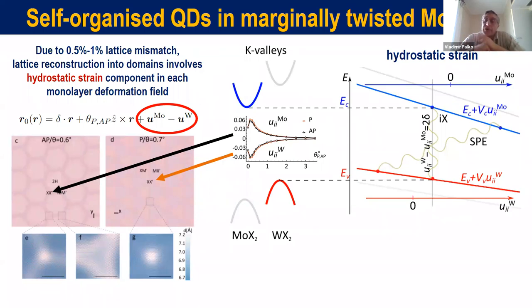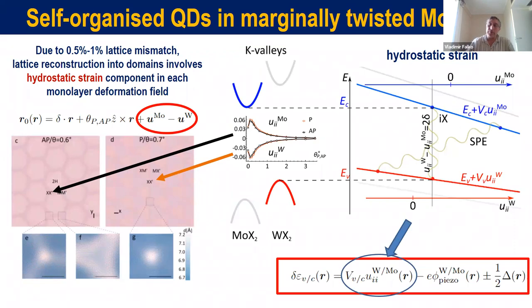They basically come towards each other, and this means that for electrons, we'll get quantum dots in those corners of the domain walls where we have XX' stacking. And for the holes, we also have quantum dots in the same place. So we are getting quantum dots for the excitons, as well as for electrons and holes, in the same place, which was not, by the way, the case in homobilayers, where the band edges for electrons and holes appear to be in different positions.